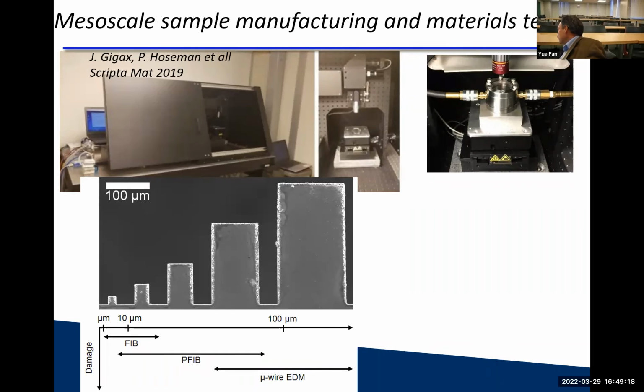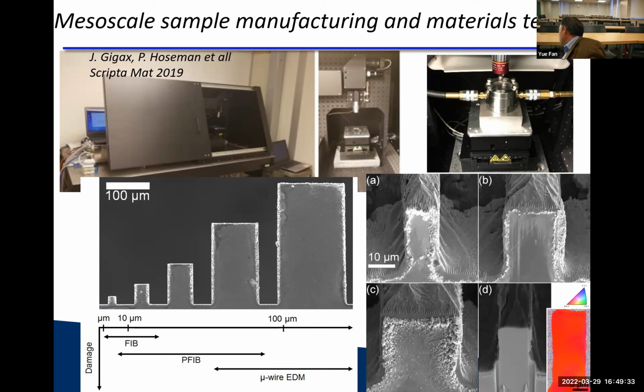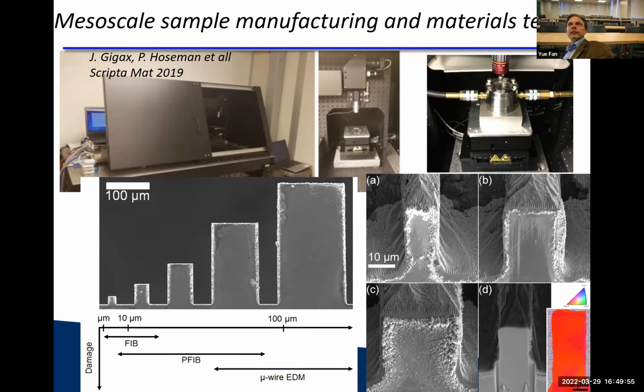Jonathan Gigax from Los Alamos and I studied a little bit what's the effect of this. So here are different pillars cut with this laser and they look pretty nice. They do sometimes require a little bit of cleanup. As you can see, the surfaces can be rough. Now, this is from 3 years ago or so, so by now we've gotten much better at this. These were really the first pillars we made. But the nice thing is we don't see any kind of recrystallization. It's all one grain. It's stayed that way and didn't really change too much. And if anybody wants to know the data, the stress strain data to these things, of course, we can discuss further, but I want to show you what the pillars look like.